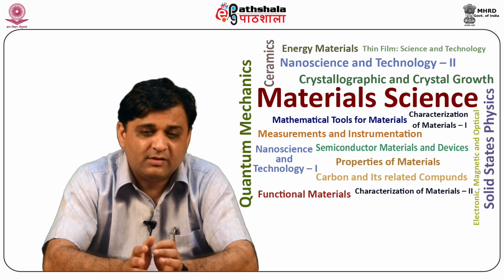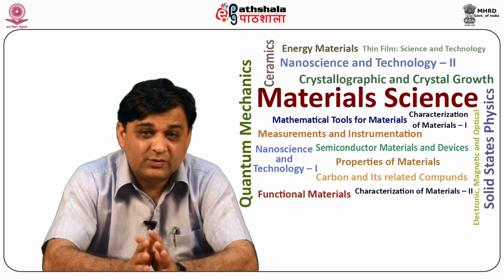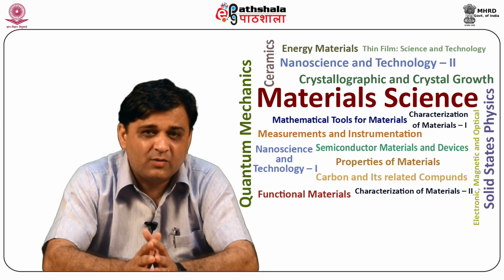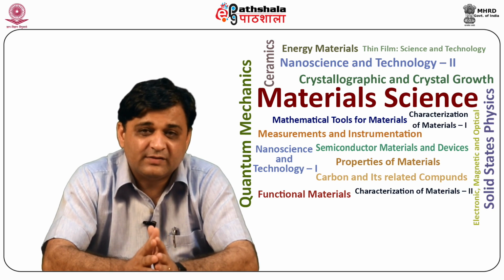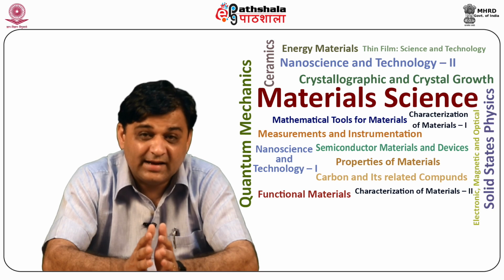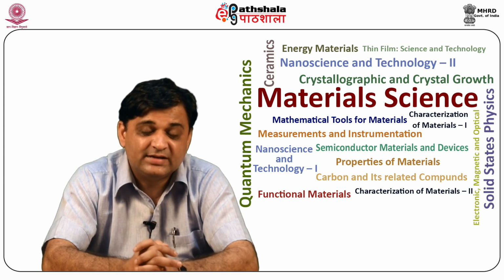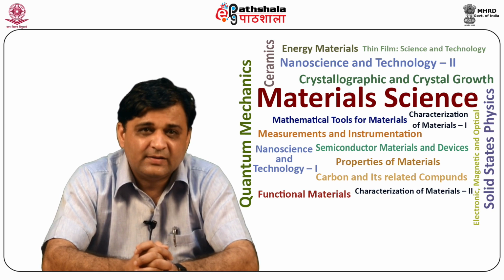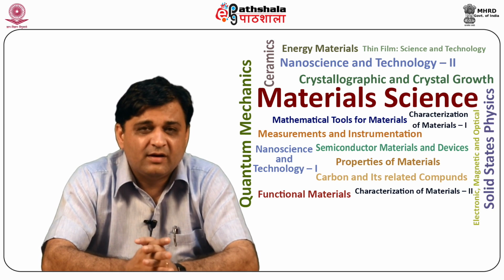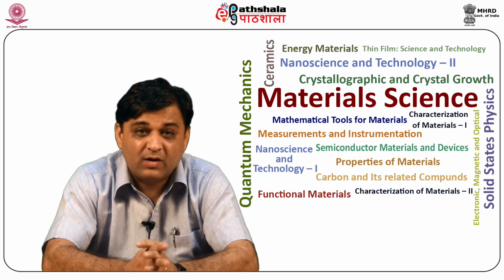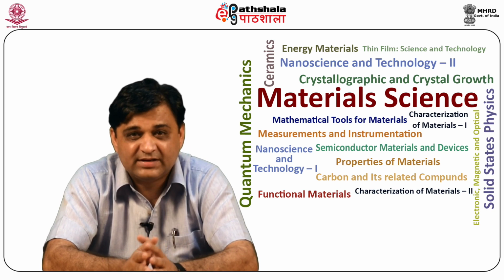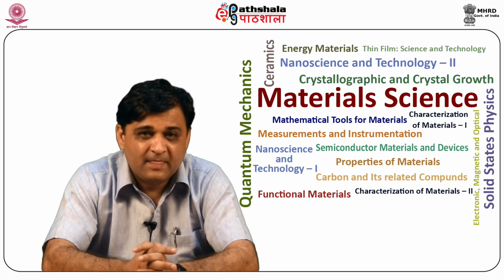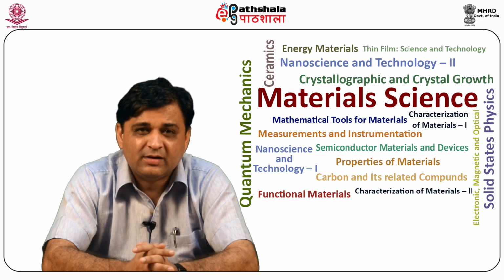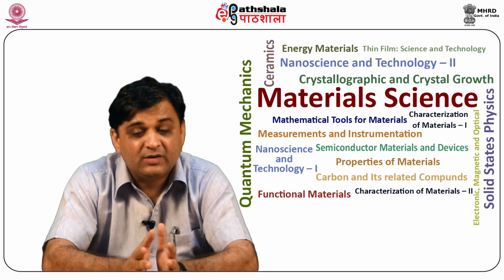Maybe if I speak in terms of nanometers, let us say 200 nanometers is the upper limit. So with these techniques we are talking about only films which are less than 100 nanometers, and their roughness, and we can even analyze atomic scale roughness. These techniques are very sensitive, and the complementary technique, neutron reflectivity, works in the same way with a better contrast that can be generated in organic samples. GID finds the structure of a 2D monolayer which cannot be identified from usual XRD machines.